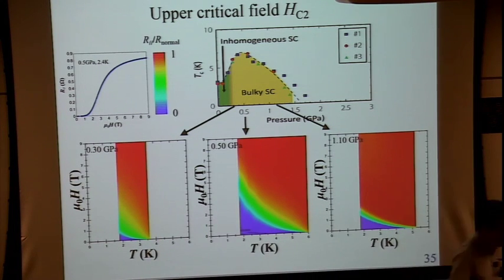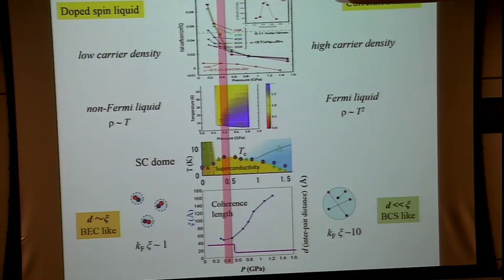And from the upper critical field, we could determine the coherence length. The coherence length, roughly speaking, characterizes the scale of the Cooper pairs. Okay? So please take a look at this one. This purple curve indicates the rough estimate of the inter-Cooper pair distance. At high pressure regions, we assume that all of the electrons participate in the superconducting state. In these regions, coherence length is much larger than the inter-Cooper pair distance. This means that in these regions, Cooper pairs are heavily overlapping, in a BCS-like state.